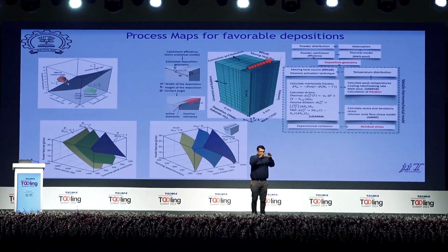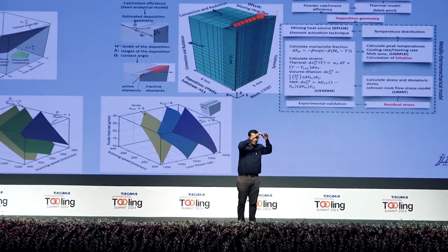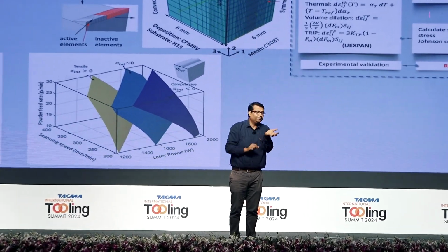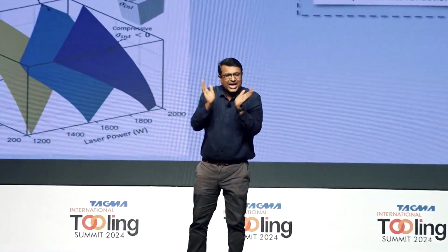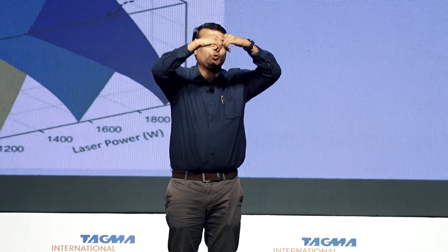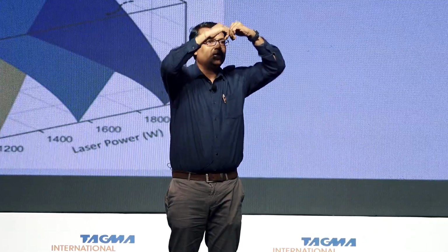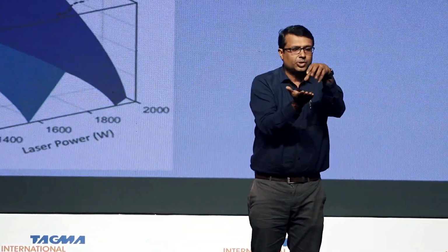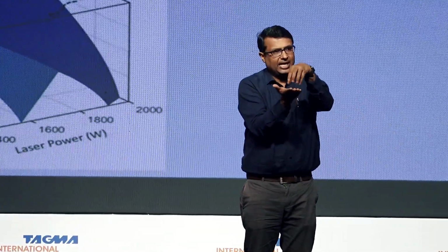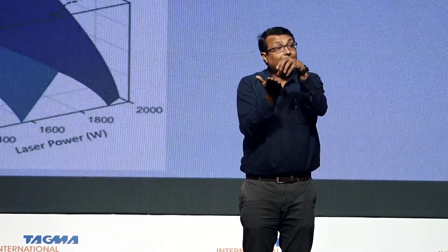The first one is, if my deposit is very, very high, then my deposition angle will be obtuse. And what will happen is, between two layers, I will have a gap. So this will create porosity. So I want to know that my deposition should always be acute. The other thing is that my depositions should also have adequate bonding. So my bonding between substrate and the deposit should be complete.